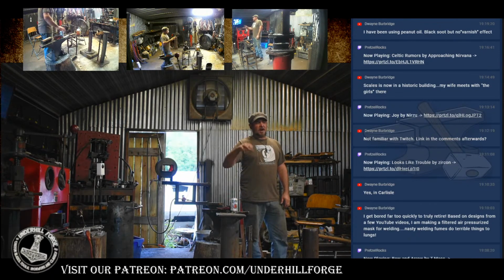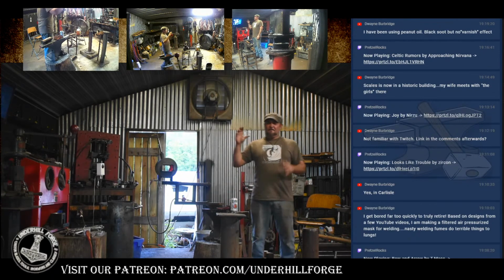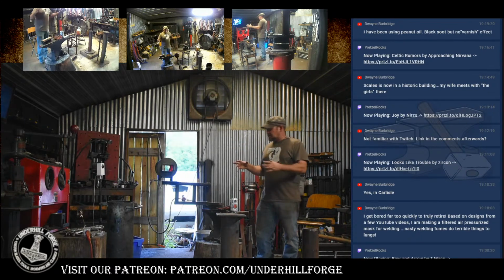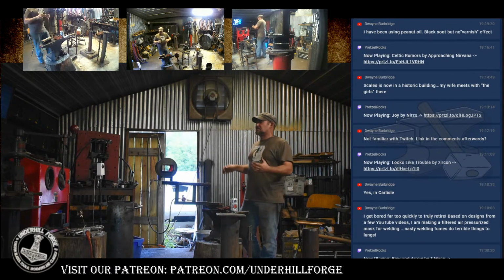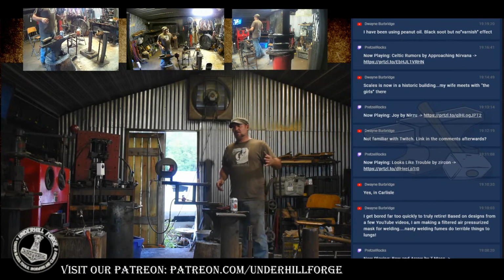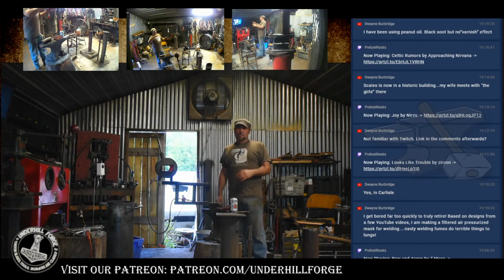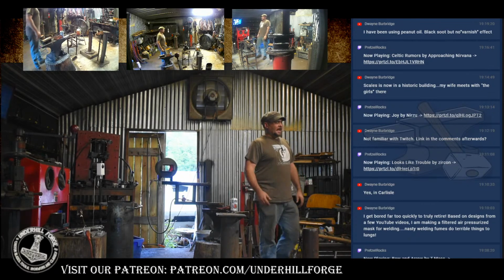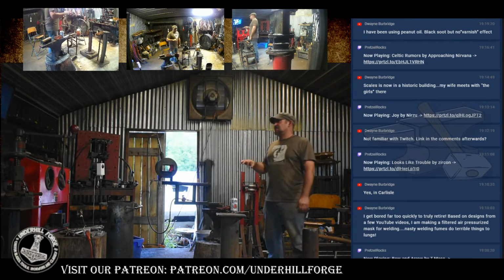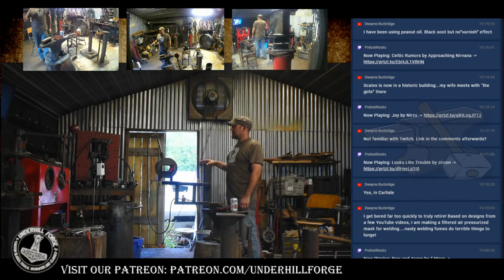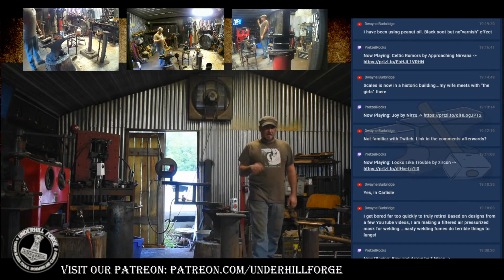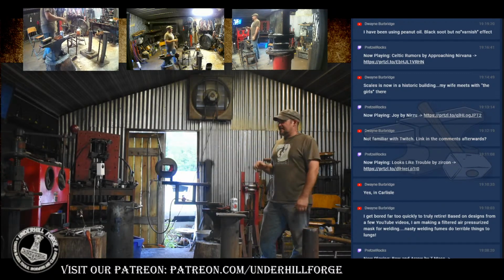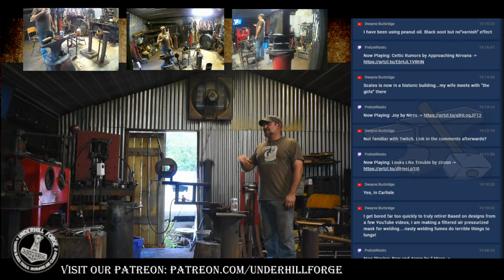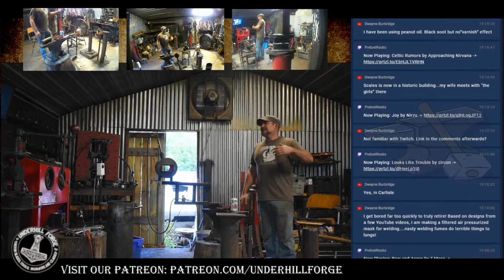The steel requires hardening at a very small window that's just a few milliseconds from one temperature to below 700 degrees. And the problem is the viscosity of the peanut oil. For steels like 1095, essentially you're getting failure, I don't know, just to throw a number out there, probably 20% of the time.